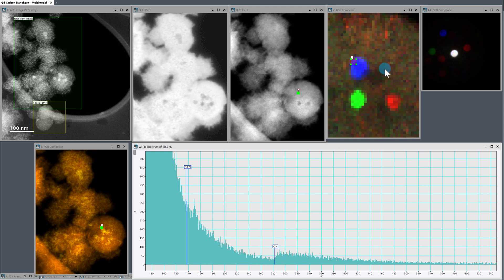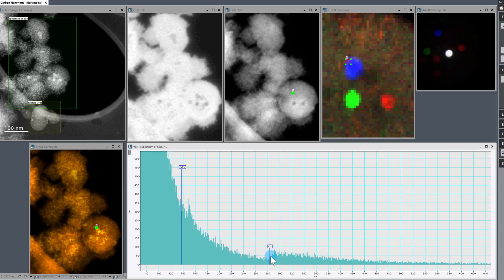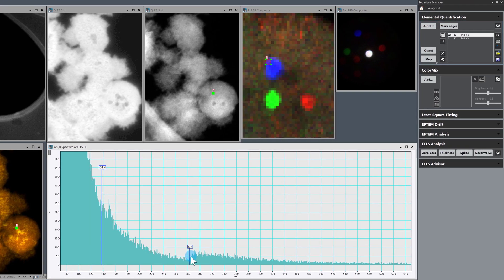The reason is that the setup here is really favoring the diffraction. We used a very small condenser aperture on the microscope so that we had non-overlapping disks in our CBED pattern. And that helps us with our CBED analysis. But it gives us a very low convergence angle, which isn't ideal for getting a really strong EELS signal. So how can we kind of help ourselves here?